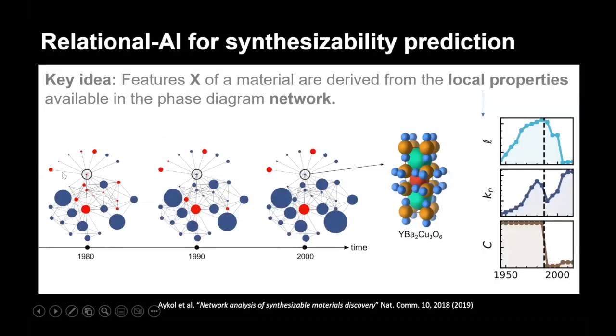Now, the connection that we're going to make with synthesizability is maybe if you watch the network as a function of time, and you look at a case where, say, a new compound appears in the network, maybe there was some hint in the topological features of the network before that compound appeared. Maybe there was some hint that something was about to appear in the network at that spot. And if so, maybe we could use these topological features of the network to help us disentangle this information and predict when a compound is likely to appear in the network.